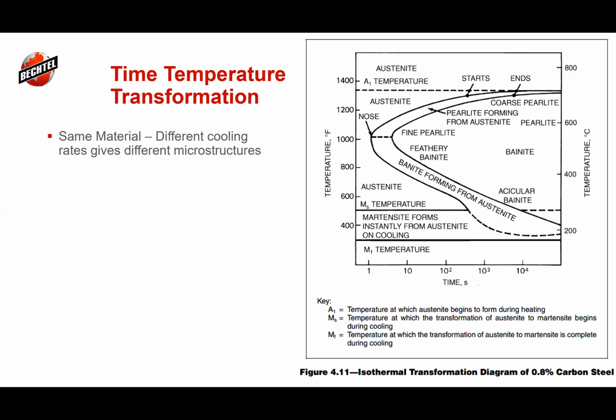I looked at the 600-some degree interpass temperature, and what they were doing on the time temperature diagram is they were keeping that heat affected zone nice and hot, right up here, for a really long time. They were coarsening, basically letting the grains grow so much that, as you can see here, it says coarse pearlite. They were just ending up with massive coarse grains, and they weren't able to pass their tensile test because they were keeping it too hot for too long. So equally damaging to letting it quench too fast is keeping it warm for too long. I don't know if anybody's had experience with that.